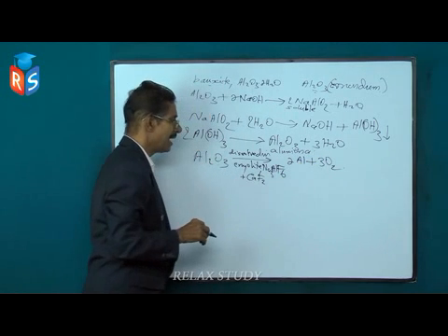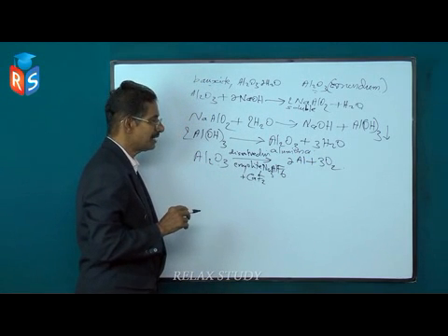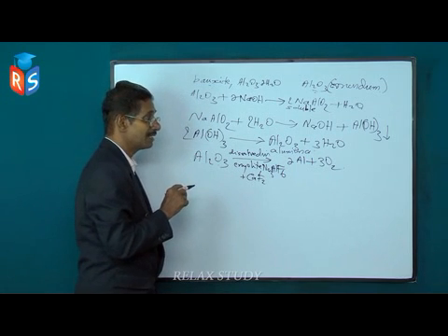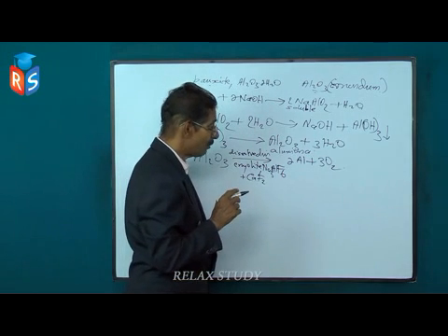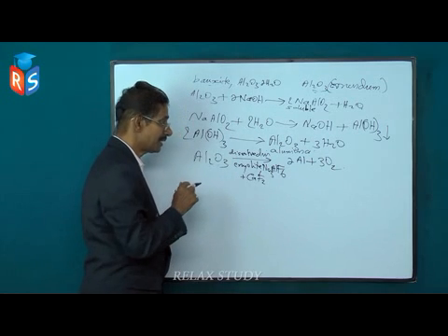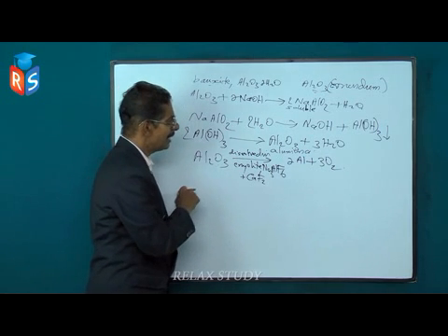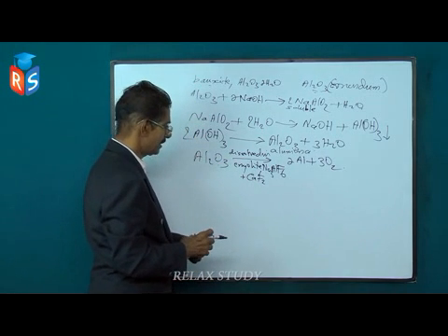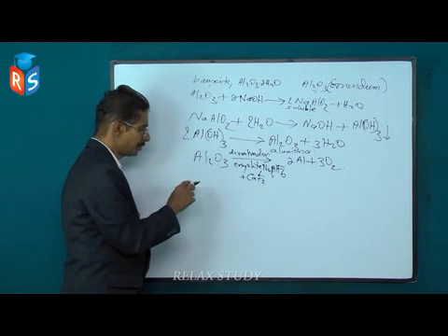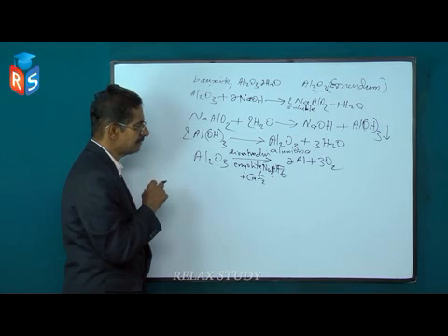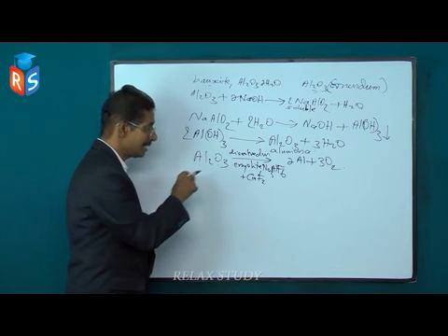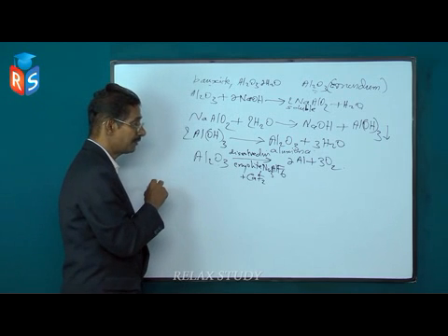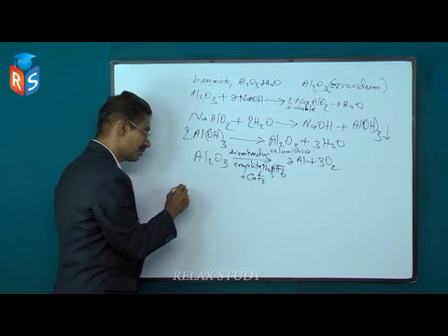As the oxygen goes to the anode, it reacts with the carbon to form carbon dioxide. That's why you take thick blocks of carbon, and when the carbon blocks making up the anode become very thin, you replace them. That's the approximate arrangement for the manufacture of aluminum. The industrial importance of aluminum is well known to you, and it's an excellent conductor of electricity. Unlike boron, which is a non-conductor, aluminum conducts well, and several alloys of aluminum are of great importance. Just a few of them I will mention.